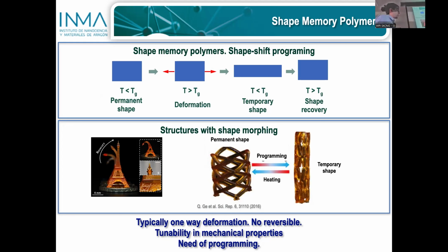You impose a deformation to the material, and while you are imposing this deformation, you cool down the material. In this way, you program the material and fix this deformation, which is released back to the original shape by heating the sample above the transition temperature.